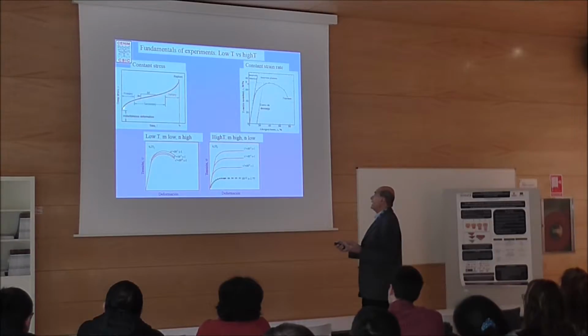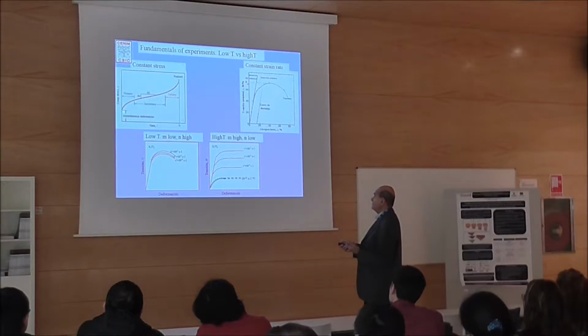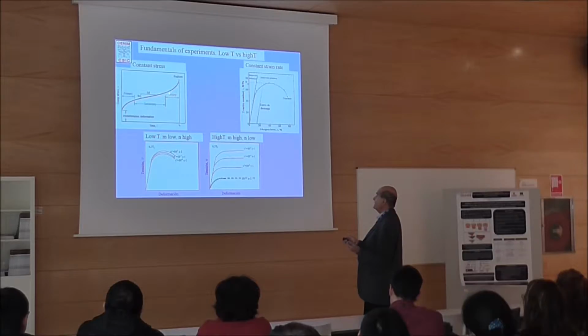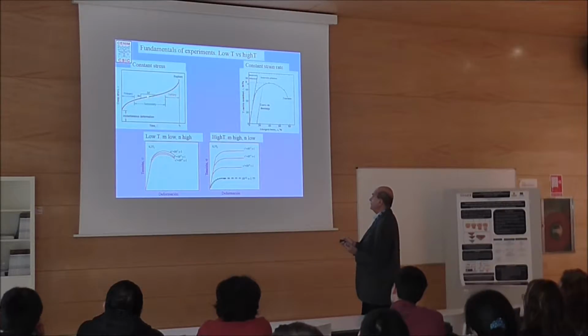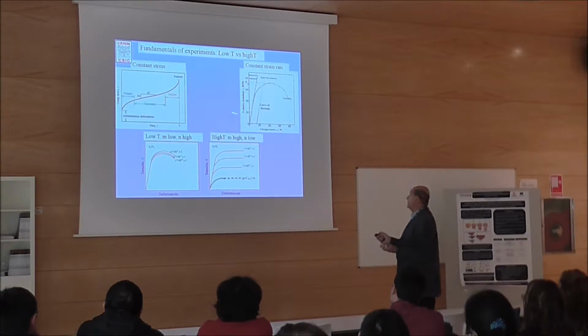What is the difference? Here I apply a constant stress. What happens is we have an instantaneous deformation, then we have a primary creep, and then we have a steady state. We always work with a steady state creep. As you can see here, the slope of this curve gives us the strain rate. So we apply a stress and we obtain a strain rate. Here is the same, but different. Here we apply a strain rate and we obtain a stress. At the end, we have strain rate and stresses from both kinds of experiments.